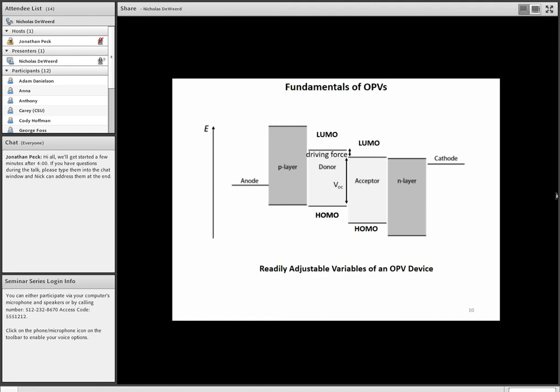And then lastly, we have a small gap between the two LUMO energies of the donor and the acceptor, and that is what we're calling our driving force. So the most up-to-date research that I'm aware of suggests this driving force has a smaller and smaller impact on the total number of charges generated in the device. So a really small driving force is actually okay. It looks like you just have to have some form of driving force, some small gap between the donor and the acceptor in order to efficiently delocalize charges.